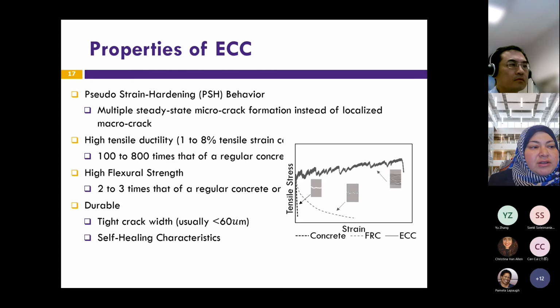So if we look at this figure right here, it compares the stress-strain behavior of regular concrete, fiber reinforced concrete, and ECC. This behavior allows the material to exhibit high ductility, which is sometimes 100 to 800 times more than regular concrete. The flexural strength also is 2 to 3 times that of regular concrete. In addition, because we are getting very small cracks instead of a major crack, that makes the material more susceptible to self-healing, or what we call autogenous healing, the formation of calcium carbonate that could close the crack,